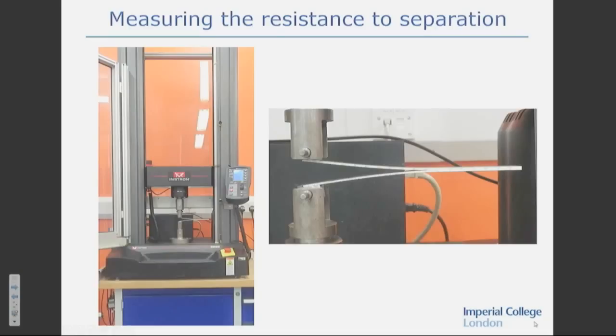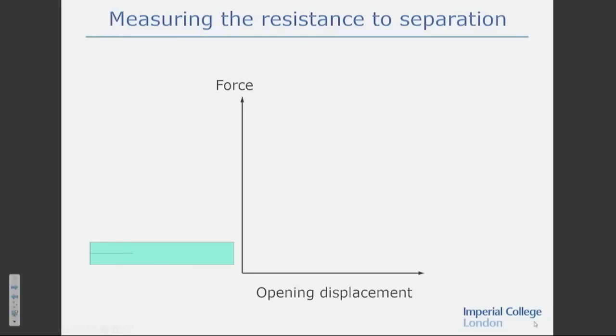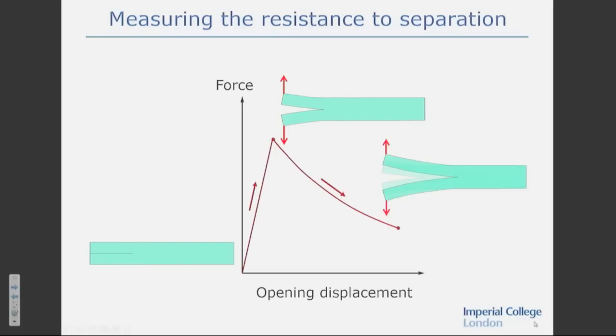The delamination or separation starts advancing along the midplane, and we monitor the applied force, the applied displacement, and the distance to the tip of the separation. So let me show you how we get this. There's the original specimen before we start loading it. This is the force, this is the opening displacement, and initially it loads up nice and linearly. And we get to a point where the crack just starts to grow, and as soon as it starts to grow, the load starts dropping. And we carry on doing this test. We grow the crack. We've grown it to this position now. The load's dropped off a little bit, and the curve sweeps down like this.